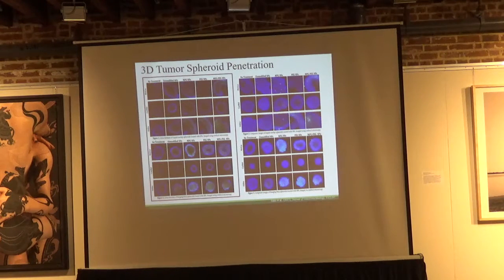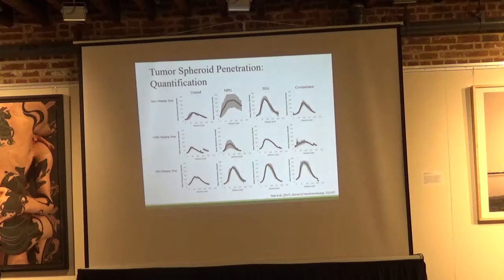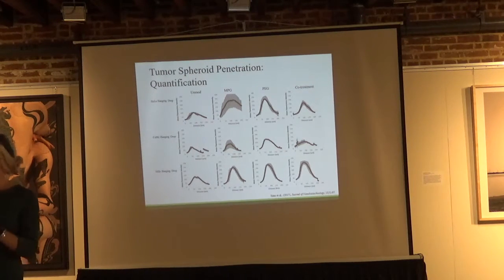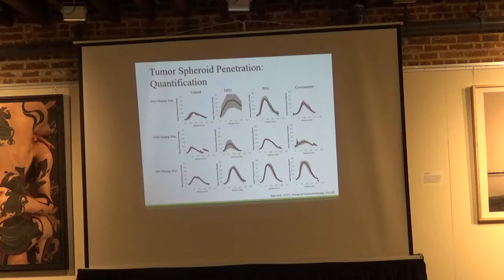We looked at tumor cross-sections on the left and composite images on the right as a function of three different cervical types of cells, so HeLa cells, Caski tumor cells, and SiHa cells. And we delivered either no treatment to these cells, unmodified particles, MPG modified particles, PEG, or MPG co-treatment particles. And so we took this data, only a subset of which I'll show today, and particularly in the hanging drop method, that allowed us, because they're smaller tumors, to enable greater amounts of particle penetration relative to liquid overlay.